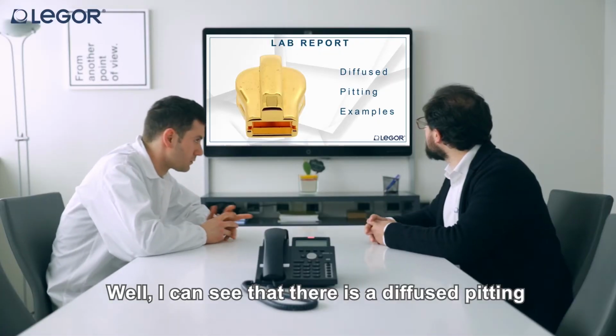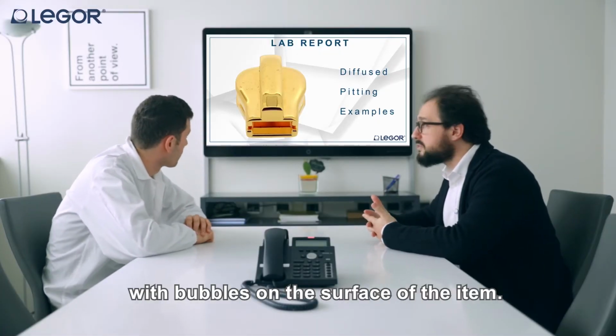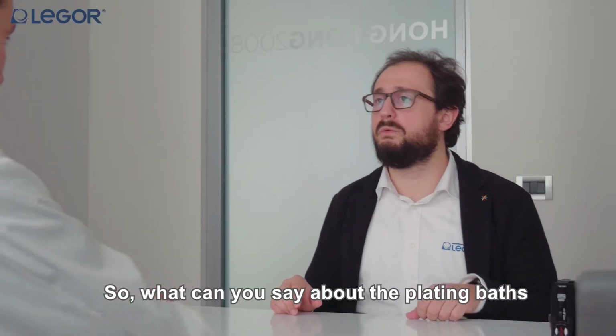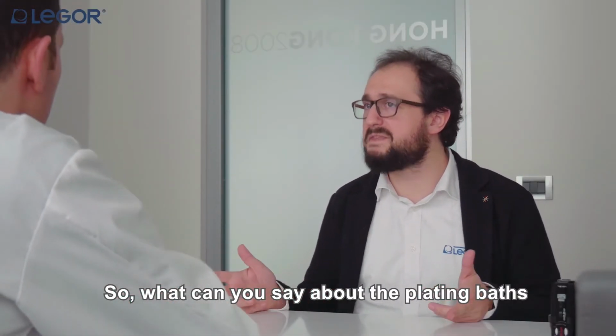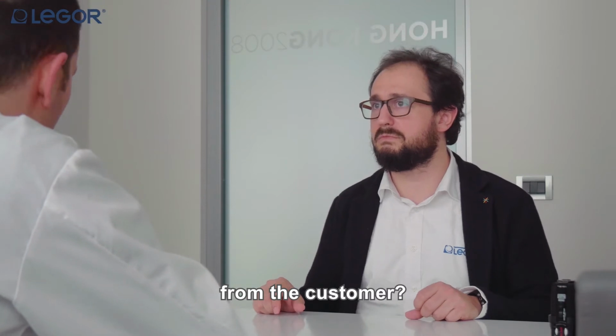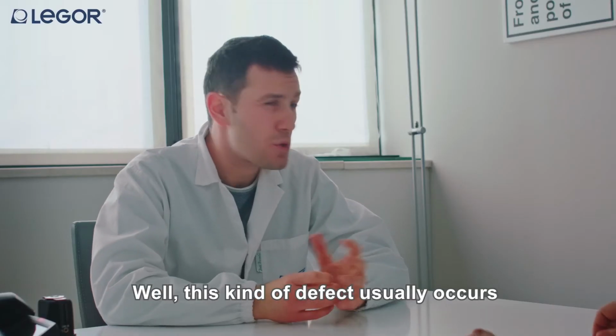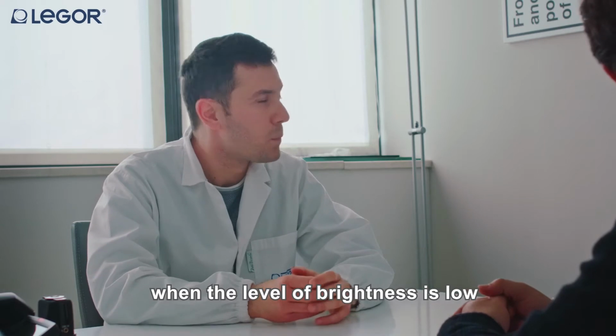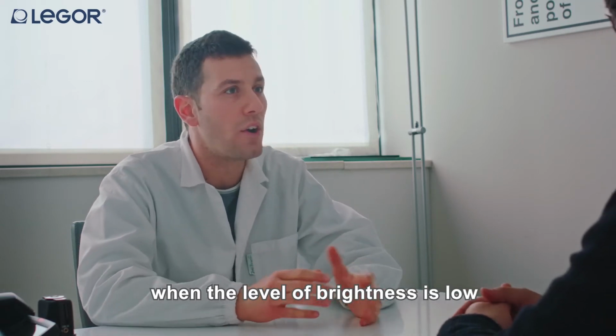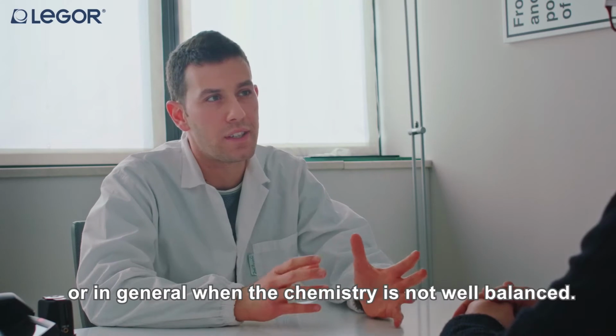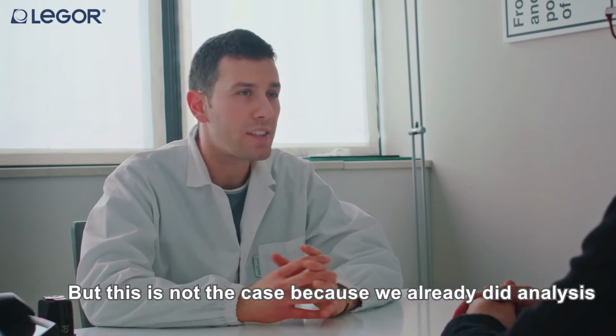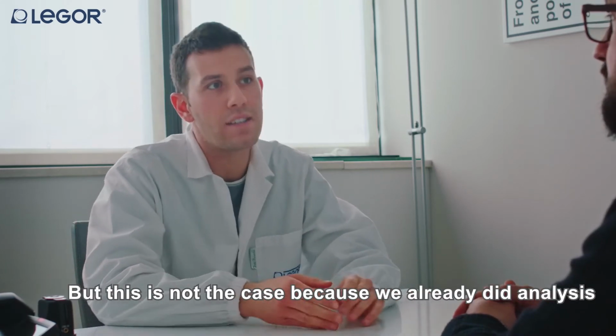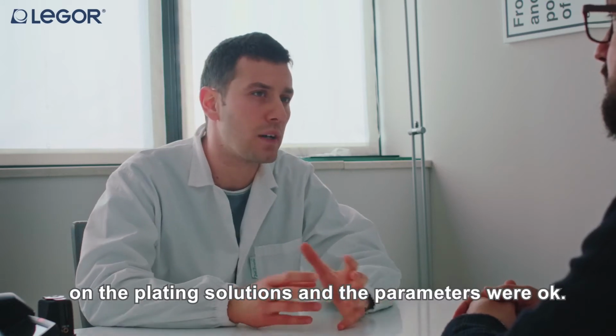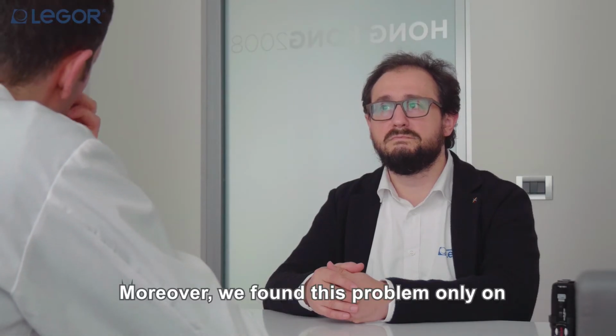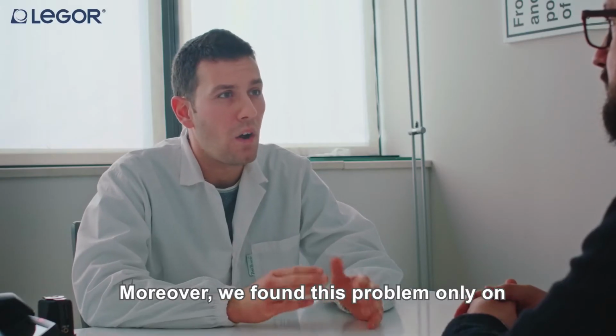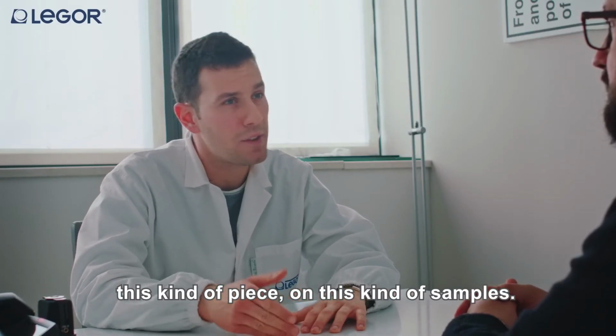Well, I can see that there is a diffused pitting with bubbles on the surface of the item. So, what can you say about the plating baths from the customer? Well, this kind of defect usually occurs when the level of brightness is low, or in general when the chemistry is not well balanced. But this is not the case because we already did analysis on the plating solution and all the parameters were okay. And moreover, we found this problem only on this kind of piece, on this kind of sample.